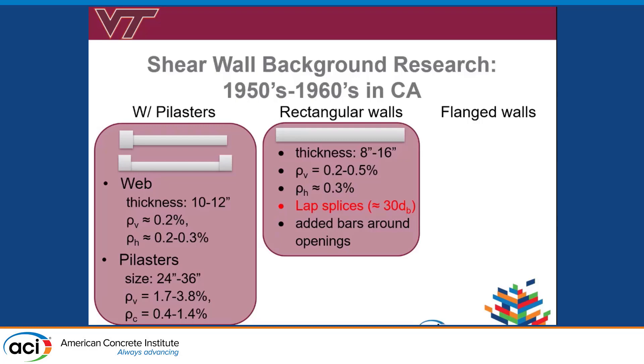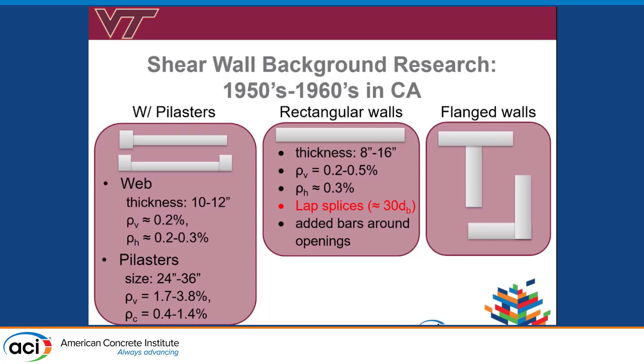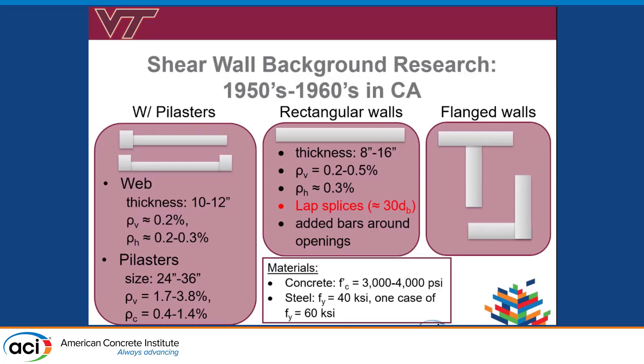We also considered rectangular walls with lap splices, because lap splicing is very common in shear walls, as well as flanged walls. Typical material properties from this time period were a lot lower than the strength we get today — concrete compressive strength was just 3,000 or 4,000 psi, and a steel strength of just 40 ksi.